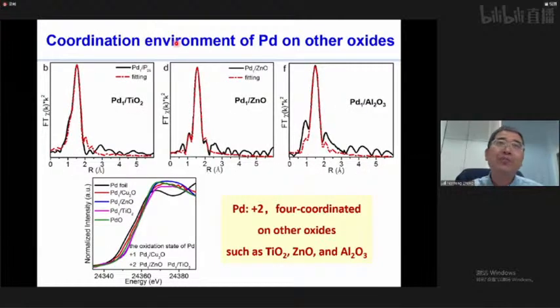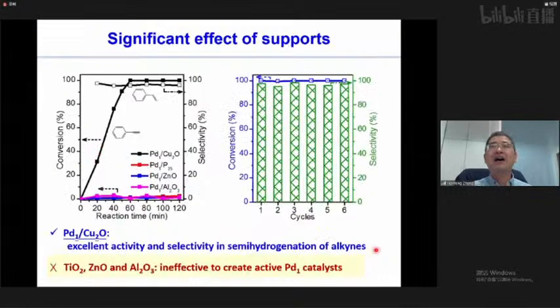But if we put palladium on other supports, like titanium oxide, zinc oxide, or aluminum oxide, they are in four-coordinated structures and +2. So it's totally different. We use this catalyst for the semi-hydrogenation of phenylacetylene. As you can see here, we mainly obtain styrene as the product. And this is what we expected, because we reduce the domain size of the catalytic metals.